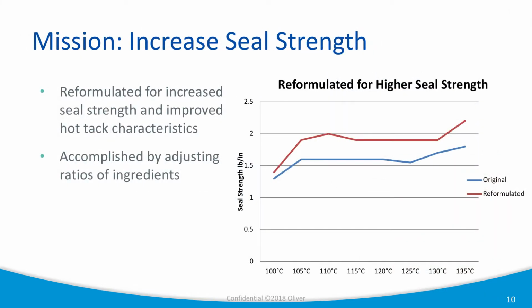So we went back to the drawing board, or back to the formulation board, and if you think about some of the things Rick just talked about, we tweaked ratios in the standard formula to increase seal strength to get us over the hurdle. This is a chart that shows seal strength output. So basically you can see the original formula is the blue line. That y-axis is the seal strength in pounds per inch. So the legacy product was tracking around 1.5 pounds, a little bit higher than that.